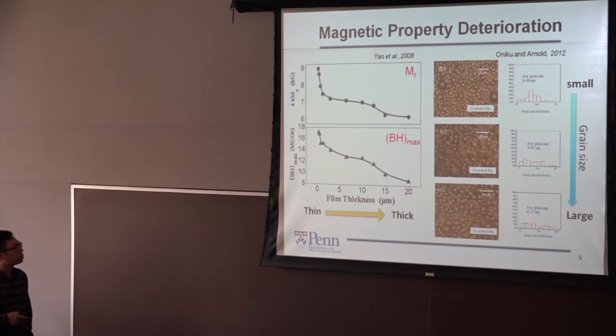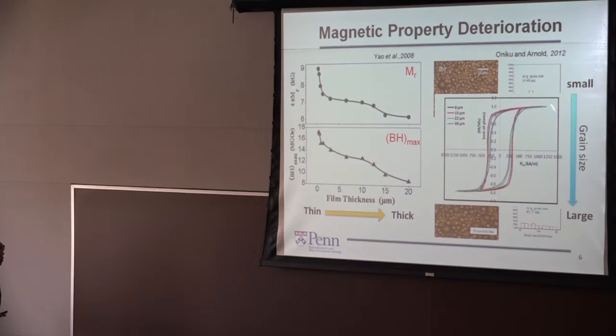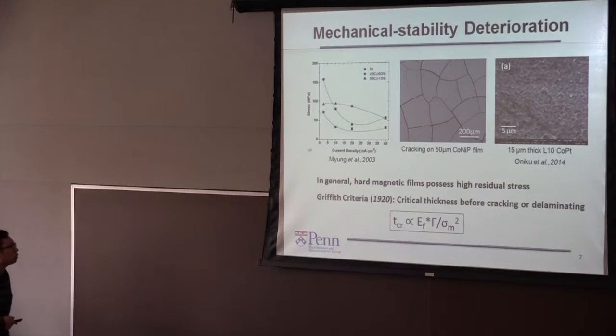And one possible explanation for this is people found out that the grain size of the film increases as the film thickness increases, and it's directly related to the hysteresis loop shape. And so for the BH max, you can see that as the thickness increases, the BH max decreases in this case. So that's not the only problem.